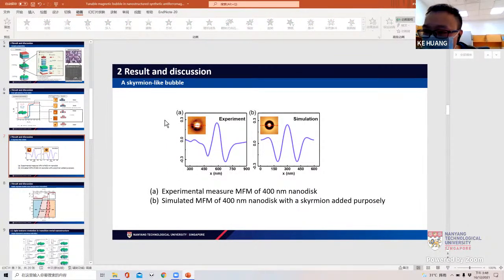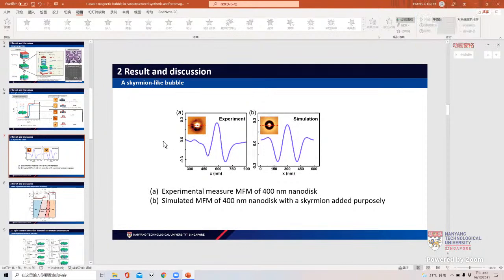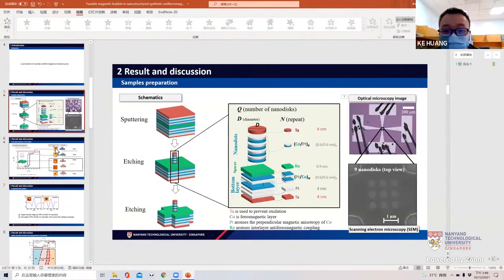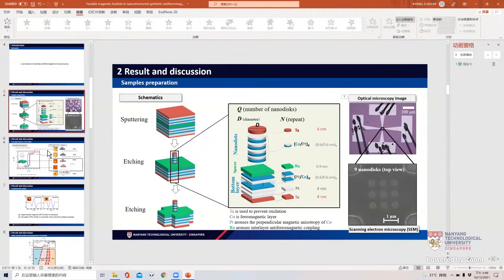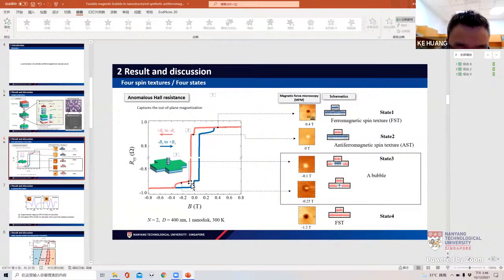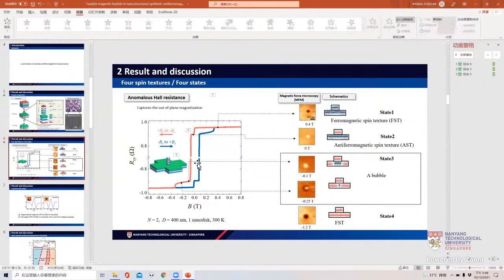So what's your next question? What is the size? This is 400 nanometer. So it occupies the entire dot. Oh, you mean what's the size of the skyrmion? Yeah. When it just nucleates, it's the same size as the nanodisk. But when we increase the field, you see that the RXY, the anomalous Hall resistivity, is decreasing, which means we are squashing this skyrmion-like bubble. So initially it's the same as the nanodisk size, but if we further squash it, it becomes much smaller. Oh, okay, I see.